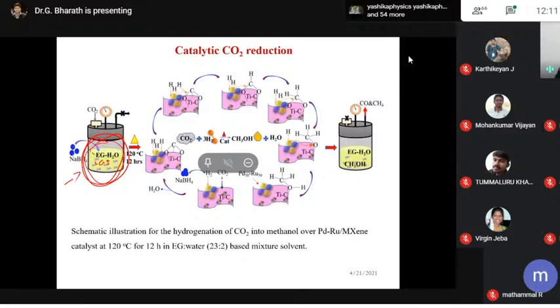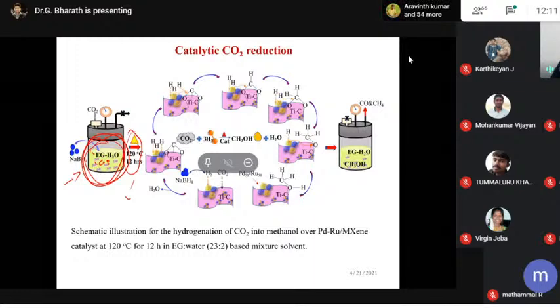The best advantage is that we use sodium borohydride as the hydrogen source. We performed this at 120 degrees and 12 hours, which is the complete reaction time. Because this is a very low reaction temperature, we can convert CO2 into methanol, CH3OH. So this is the complete process.